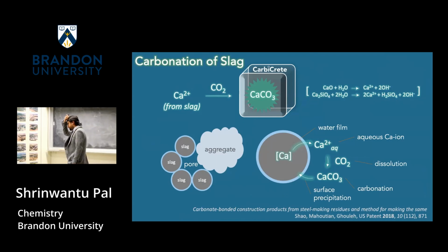As a spin-off of McGill University, one of the founders of the company I worked at in Montreal discovered that you can essentially take the blast furnace slag, grind it up, and expose it to CO2 in the presence of water, and that would actually fortify. I won't go too much into the reactions here, but the top reaction is essentially very similar to the hydration reaction that happens in cement.